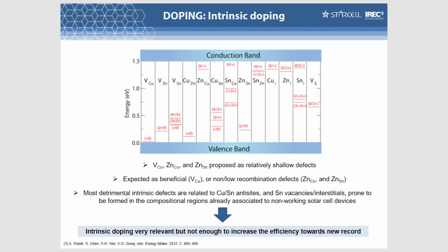And this, of course, is in agreement with other theoretical work that demonstrates that all the defects that we expect in these compositional lines are mainly shallow defects, and that we minimize the probability of formation of the defects that normally are very detrimental. We have worked a lot with that in several groups, and we think that in terms of intrinsic doping and control of composition of kesterite, we know a lot. And that modifying only this intrinsic doping is almost impossible to increase further our efficiency.